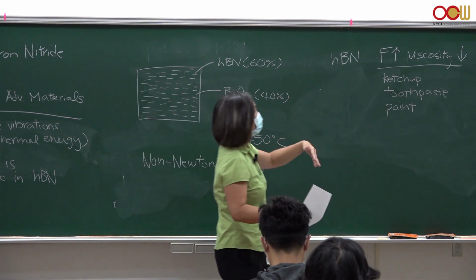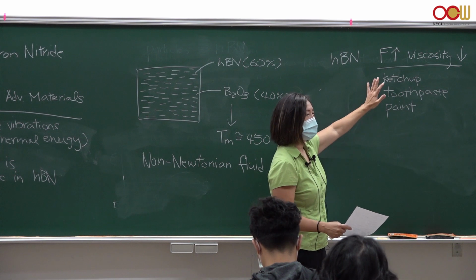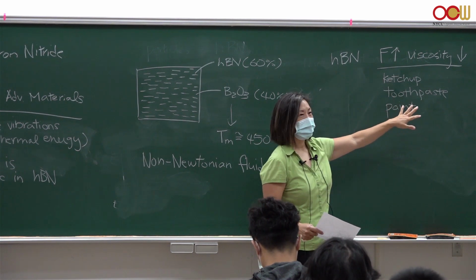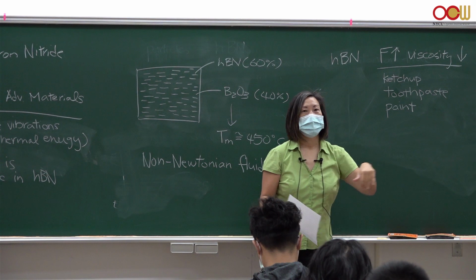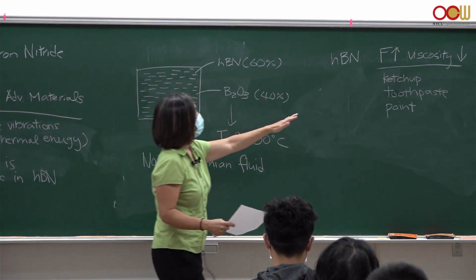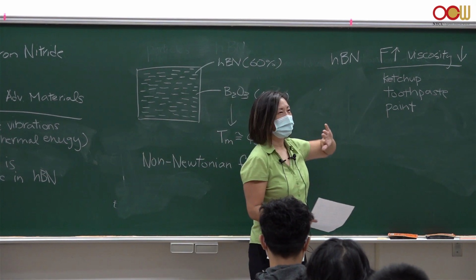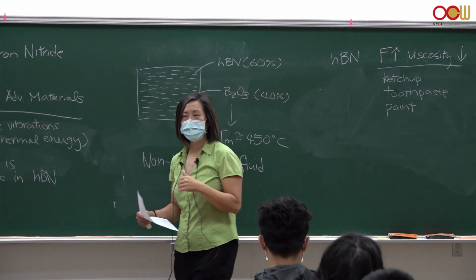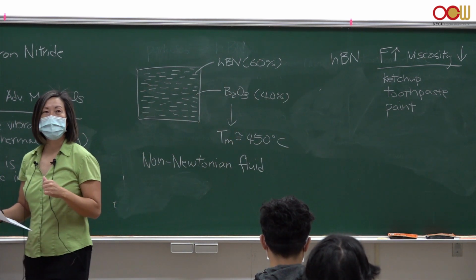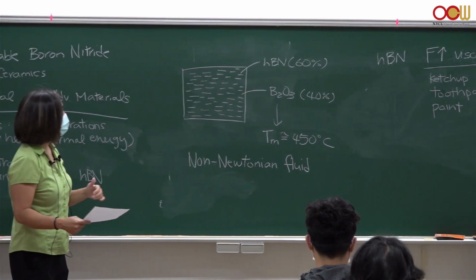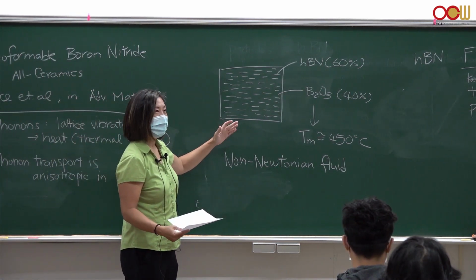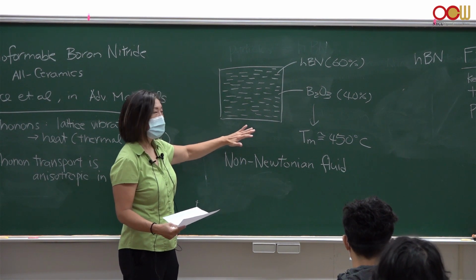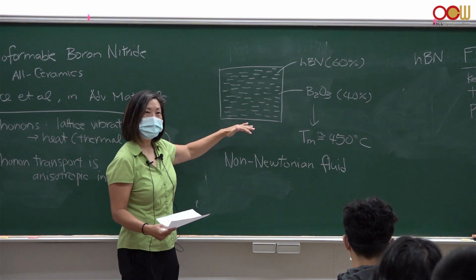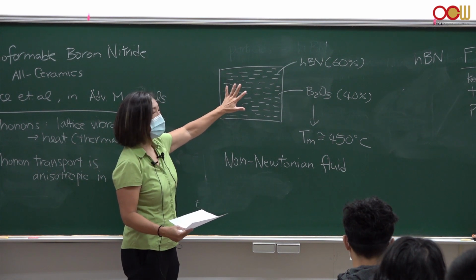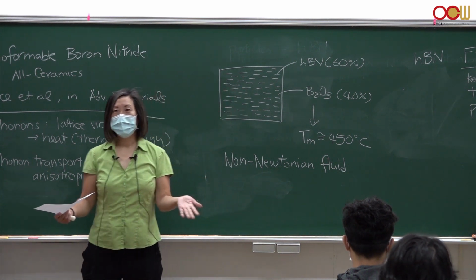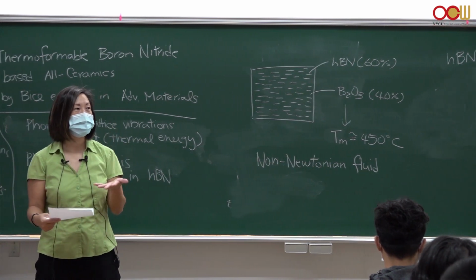So we have lots of things in our lives that are non-Newtonian fluids where, as you increase the force, the viscosity decreases. So that's what the hexagonal boron nitride is. It's a non-Newtonian fluid which decreases in viscosity when you increase the force. So that's what they found. They heated this material. The boron oxide melts at 450 degrees. But the material itself doesn't change because it has all this boron nitride inside.